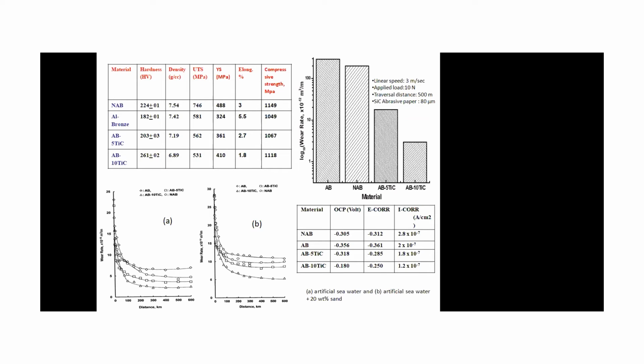So if you make a calculation of the specific strength of the composite, it may be higher than your alloy. In the case of changing from alloy to composite, we have to see not just the strength but the specific strength, the strength divided by the density. That we have to see. So that is increased. Also, compressive strength also increases. So this is what we have done in one of the projects.